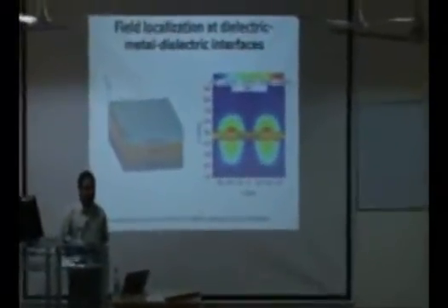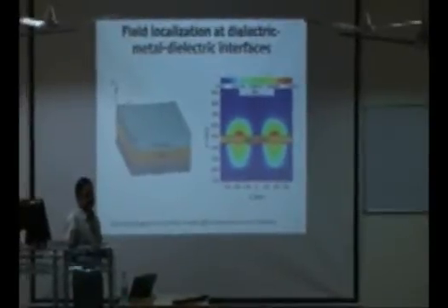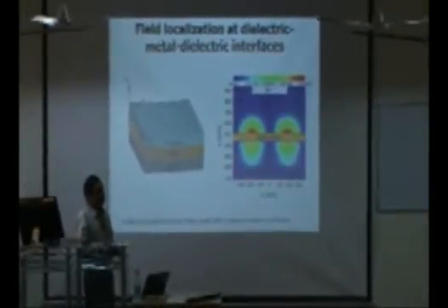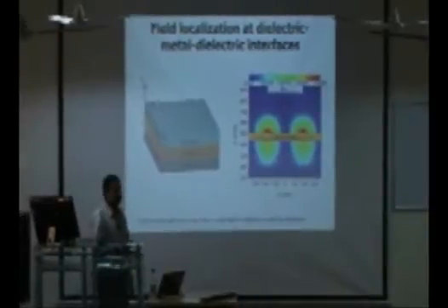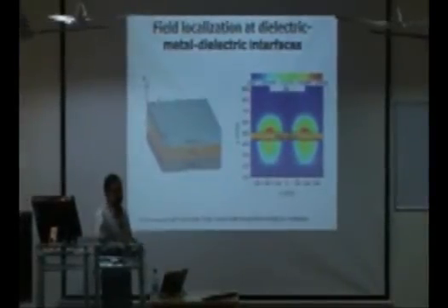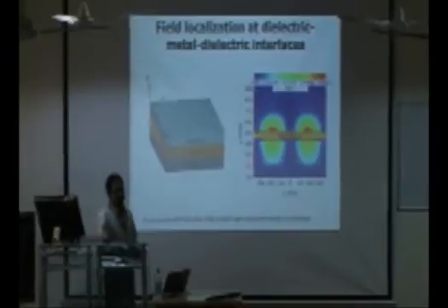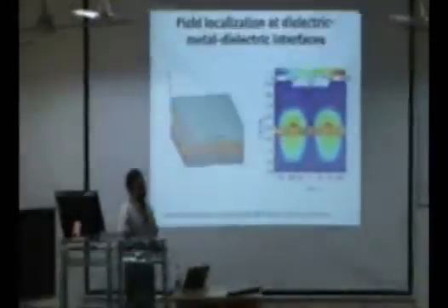And the second question, this TiO2 you said is a nanoparticle. Is it some different phase? No, TEM showed that they're completely rutile. XRD shows it's completely rutile. The XPS shows that the binding energy is shifted by about 0.5 eV.